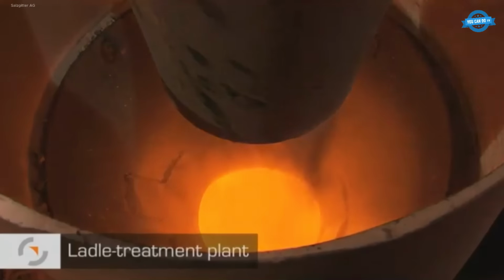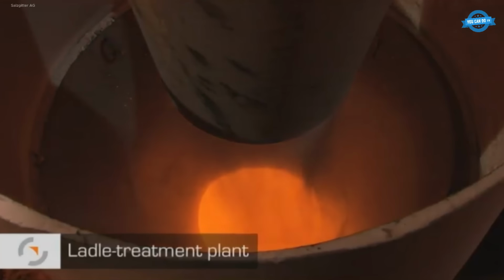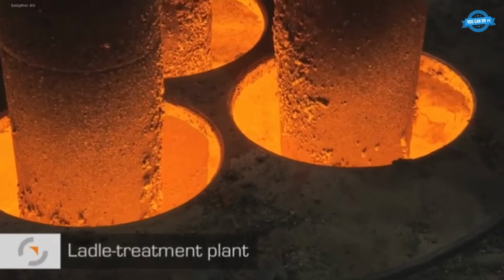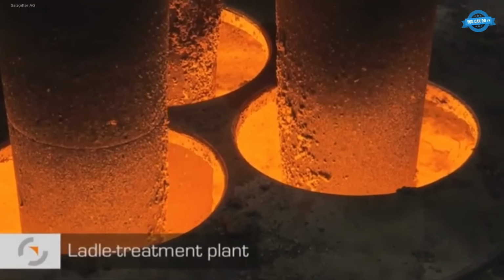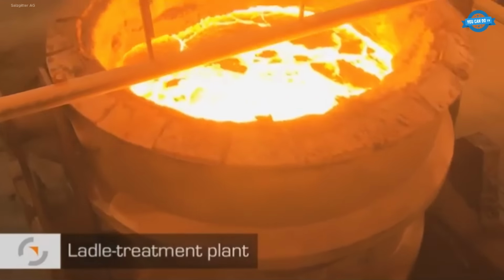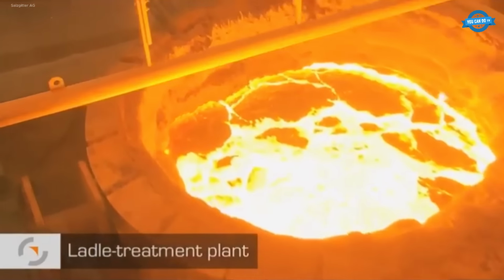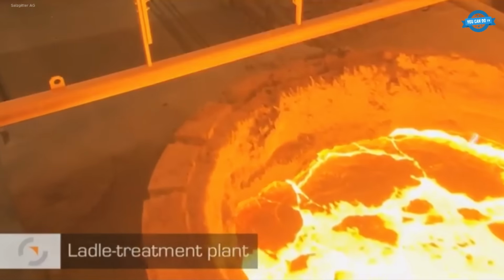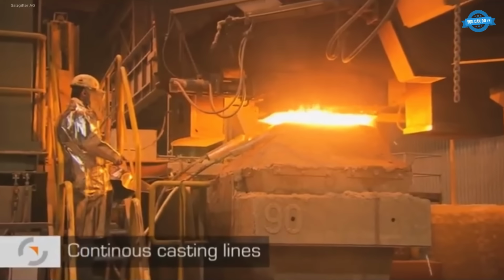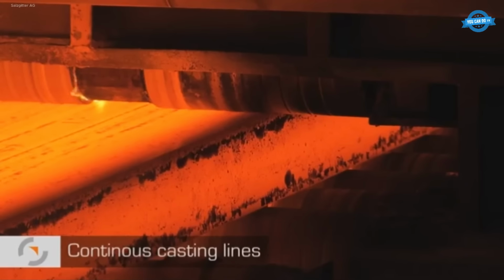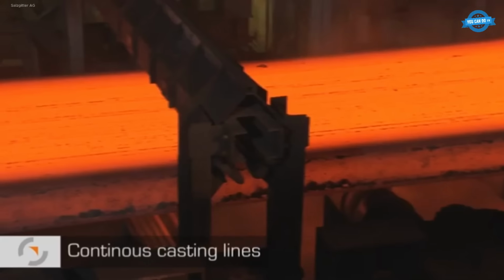The molten pig iron is transferred via torpedo ladles to converters. Salzgitter operates 3 LD converters where pure oxygen is blown into molten iron, raising the temperature to about 1,700 degrees Celsius and removing impurities through the carbon drop process. This conversion takes about 40 minutes, producing crude steel.